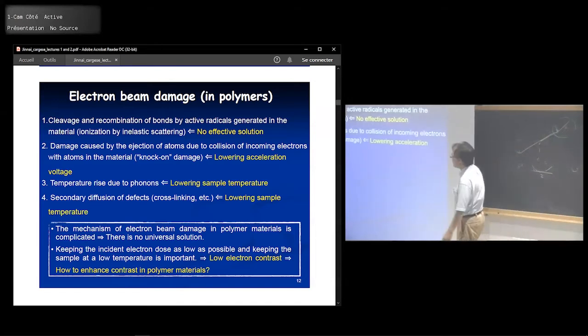The second one is what we call knock-on damage. When we put the electrons into the sample and an atom is kicked out, that's the knock-on damage. And to prevent or lower that, we need to lower the acceleration voltage. So it's always a discussion whether you're going to use a 60 kilovolt TEM or a 200 kilovolt TEM. The answer is here. If you are talking about electron beam damage, lowering the acceleration voltage is better.